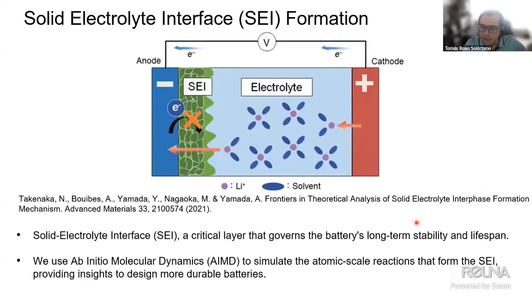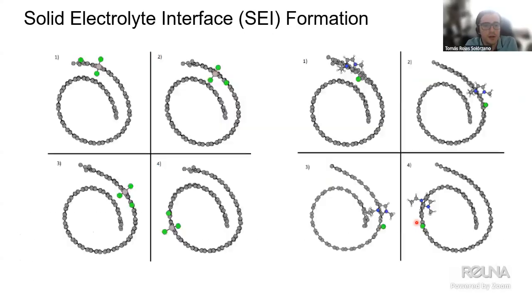Then again, like I said before, what we want to do is take that and use it as the base to see what else can happen, and moreover, what species can be produced in the SEI layer of these type of systems. What we did first was taking molecules and placing them just over the edge of the scroll. So here what we do is an AlCl3, which is the typical molecule used as the ion in this type of system. Eventually, during the processing of the battery, the AlCl3 becomes an AlCl4.